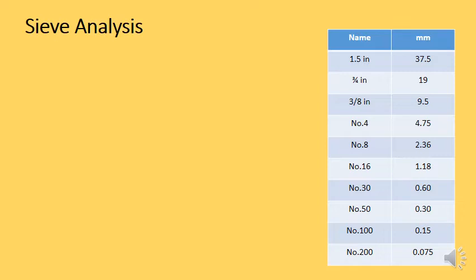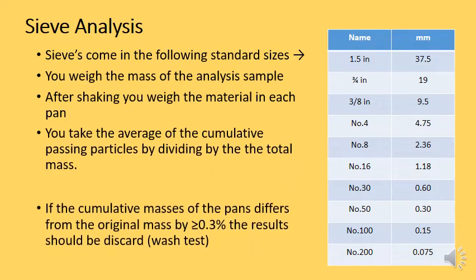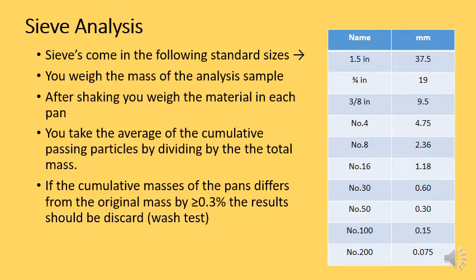Now one thing you need to know about a sieve analysis is that the sieves always come in standard sizes. And they're really confusing sizes. They are 37.5 millimeters, 19 millimeters, 9.5 millimeters. These are odd openings. Why aren't they 40 millimeters, 20 millimeters, 10 millimeters? Well, the reason for this is that the science of a sieve analysis was developed in America. And in America, they still don't use metric units. They still use imperial units. And so they based their sieve openings off inches rather than millimeters. And so that's why we have very odd opening sizes. That's just something you need to be aware of.